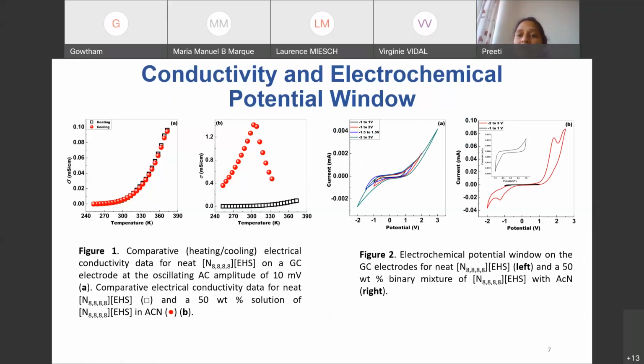So we have measured the electrochemical potential window sequentially for different windows for this neat ionic liquid. And we can go from -3 to +3. I haven't shown -3 here, but we can go from -3 to +3. And when we use the binary mixture with this solvent, we cannot go beyond -1 to +1. As you can see, if we go beyond -1, or from +2, some peaks are observed, which might be due to the acetonitrile, but we cannot consider that as an electrochemical potential window for the supercapacitor device. So for the safer side, to avoid polarization, we have used a window from -2 to +2 for all electrochemical studies for this particular ionic liquid.